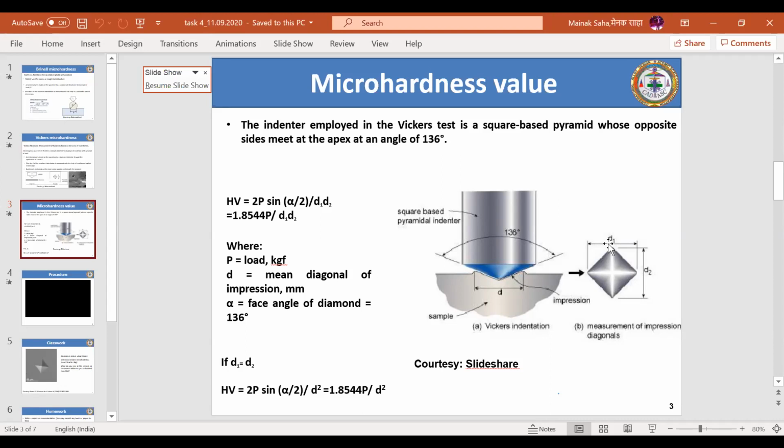If you talk of statistics, you are within error limits. And similarly, I went up till 10 kg of load and I went up till 220. So, okay, so fine. But again, if you are having a variation of around 50, you can call it a significant variation. But less than 50 in any hardness testing method, you can't call it a significant variation. So that will rather lie within the error limits. Okay. So that's the enormous advantage that this Vickers microhardness testing offers you.